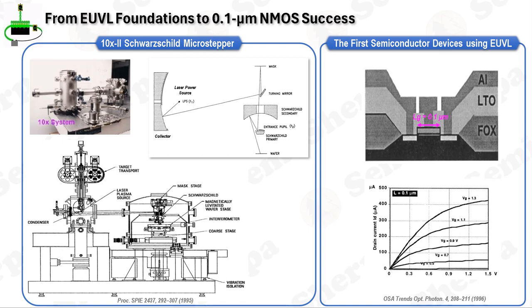In 1995, D. A. Tichenor and his team at SNL developed the first EUVL laboratory tool, known as the 10x Schwarzschild. This tool combined near-diffraction-limited imaging with a 0.1 micrometer resolution, accurate stages, and an integrated alignment system. The EUV light was sourced from a debris-mitigated laser plasma, which was achieved by focusing a neodymium-doped yttrium aluminum garnet laser on either solid xenon pellets or a high-density gas jet. This setup allowed for about 1,000 exposures without the need for condenser maintenance.